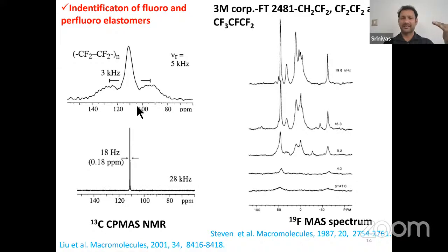Depending on the nature of the system, you can increase the spinning speed. Let us say this left side is the CF2 system. By increasing the spin speed, on the top system, around 120 ppm and 100 ppm, you think that these are the peaks if you are spinning at 5 kilohertz. But if you increase the spinning speed, you will see a single peak. This is 13C CPMAS NMR, and this corresponds to the CF2 system.